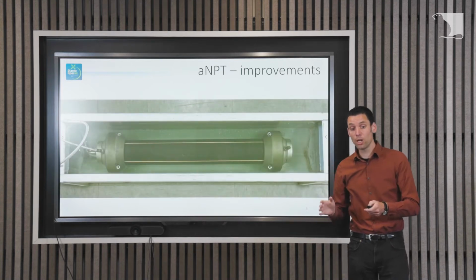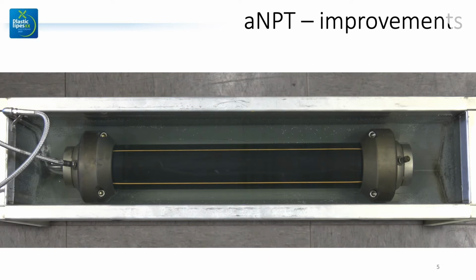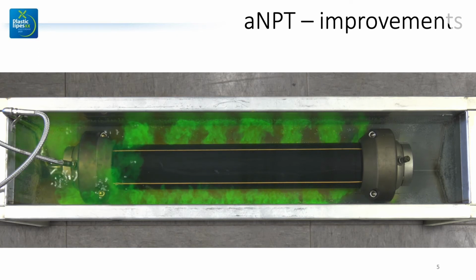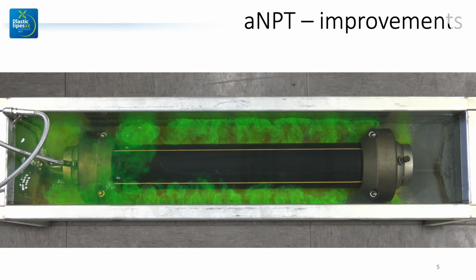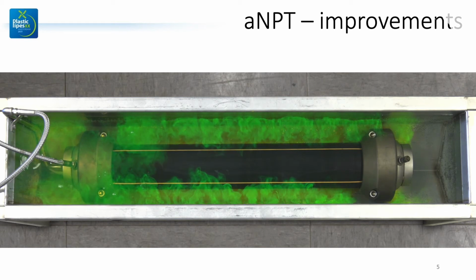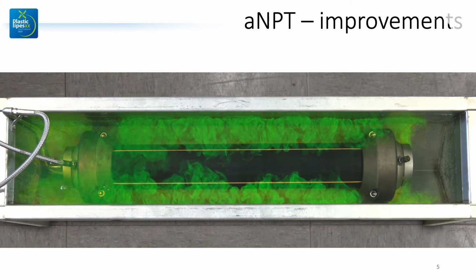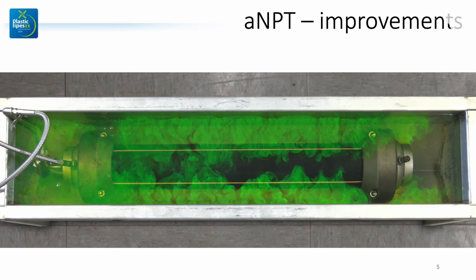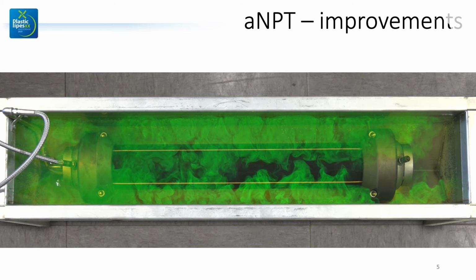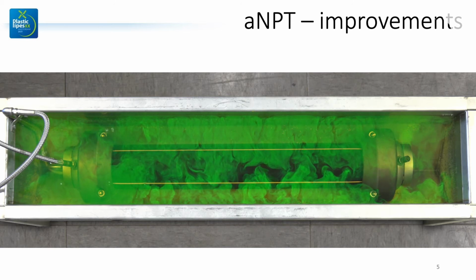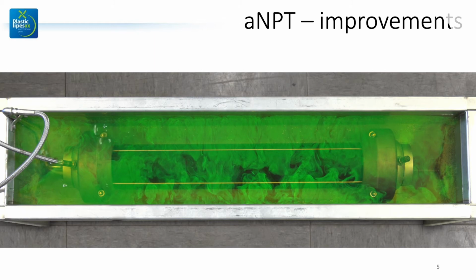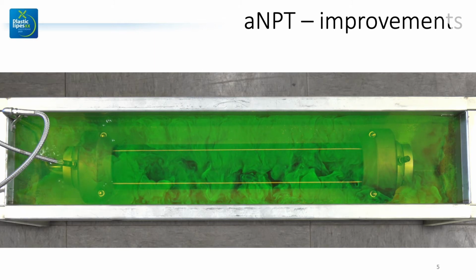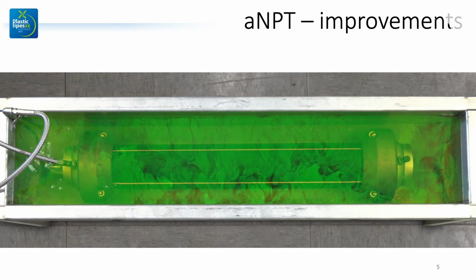So here we see that smaller container, we see a polyethylene pipe in the middle and we have end caps. And what we're doing now is we're letting that detergent solution enter that container. So you see really, it's not the detergent solution, it is the colorant. Here you see the green colorant circulating very nicely around that pipe. It comes to all the areas in the smaller container. So actually in a few minutes' time, the complete container is completely green and it's all homogeneously distributed.